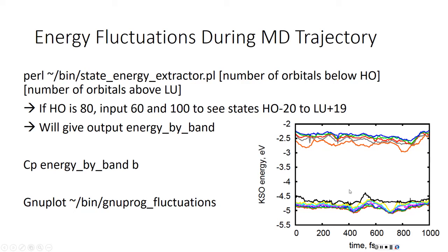So the project, Aaron is so humble that he gives examples of projects of others, but he's running a project on quantum dots that we discussed 3 weeks ago here. And if a quantum dot doesn't have ligands on the surface, there appear states that come inside the gap, close the gap, make it dark, right? If during molecular dynamics one of the ligands from the surface detaches, the surface state is recreated, and one would immediately see it on such a diagram.